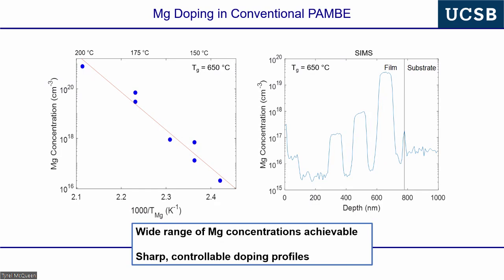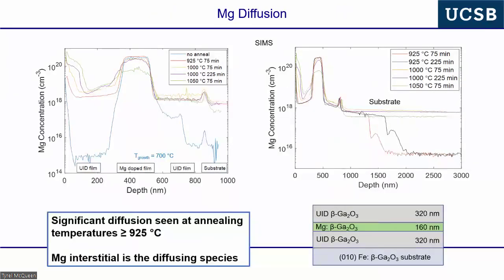We have secondary ion mass spectroscopy at UCSB. We sputter the material and look at the ions coming off quantitatively in a magnetic sector SIMS, and with implant standards we get the concentration in the semiconductor. So this looks very nice. Then we can look at the dependence on Arrhenius plots of the magnesium incorporation with the magnesium flux, which is just subliming off of solid magnesium. This all looks fine, and we get the expected apparent activation energy. And it's very interesting. If we look at these profiles of as-grown material, amongst friends, if I plotted this on a linear scale, you would see a beautiful top-hat profile. When you look at a log scale, you start to see somewhat ugly surprises, but it's still fine.